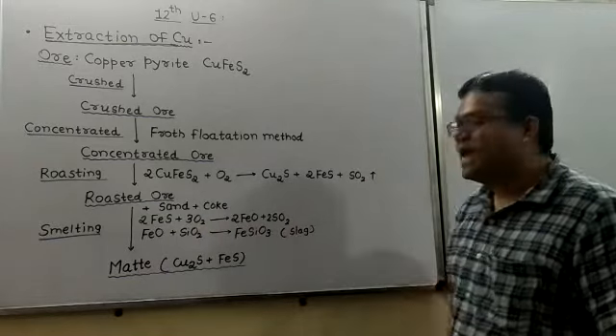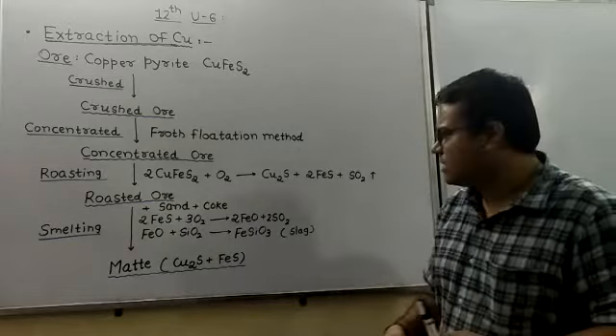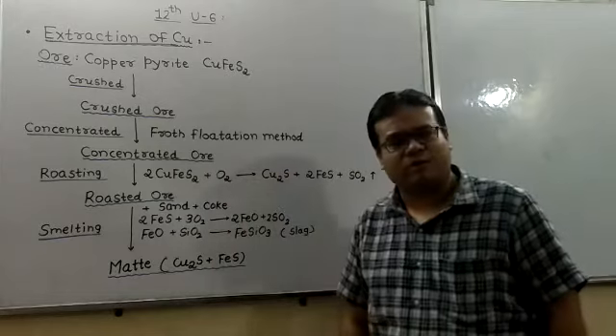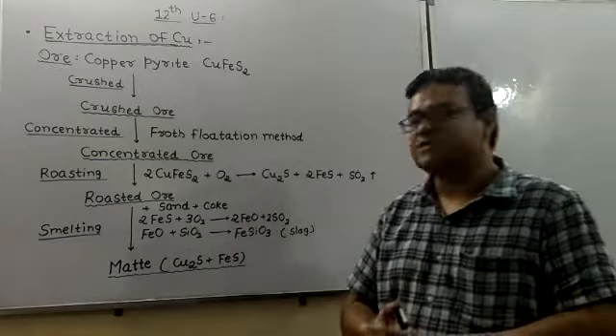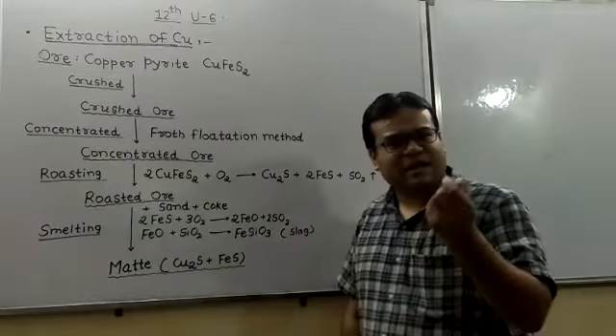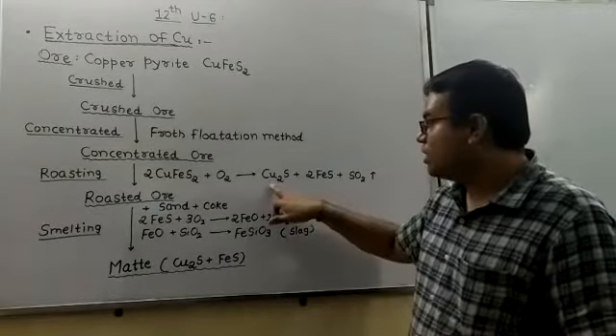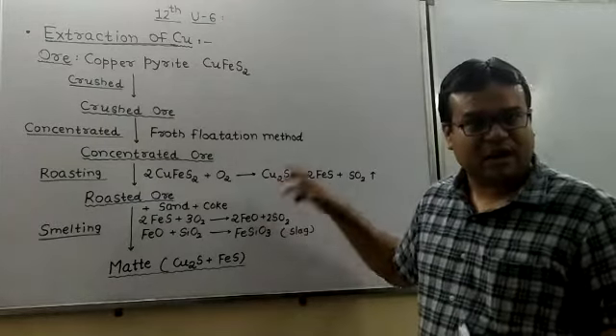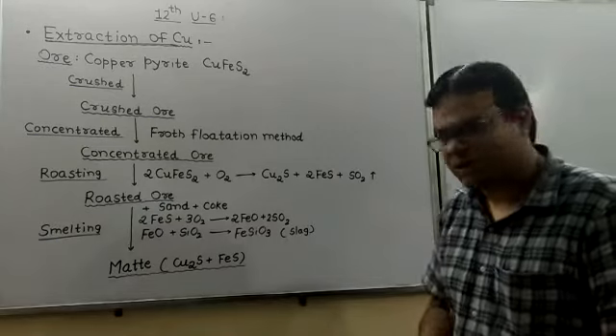Maybe a question arises—I want to clarify this stage: even though we have oxidized, why are oxides not forming here? At the stage of this particular roasting reaction, if the mixture contains even one percent of iron sulfide, it will not allow conversion of cuprous sulfide into its oxide because copper has very strong affinity for sulfur and iron has very strong affinity for oxygen.